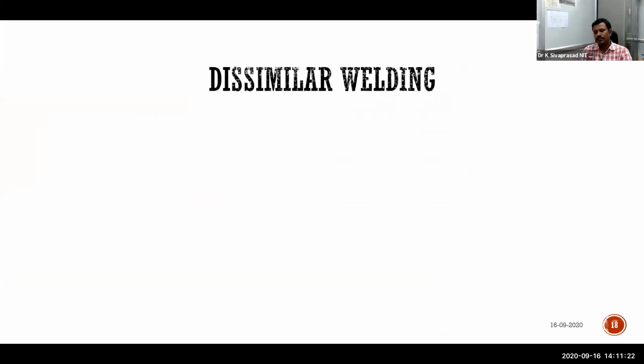So this is just a brief on dissimilar welding of the 0.5 aluminum high entropy alloy system. In both cases, 85% and above weld joint efficiency was observed, which is really uncommon in conventional systems, and this was possible only because of the formation of a single phase FCC structure. That is the reason I strongly believe that those who are working in welding should fairly develop their metallurgy skills, so that it will help you interpret your results in a more accurate and precise way.